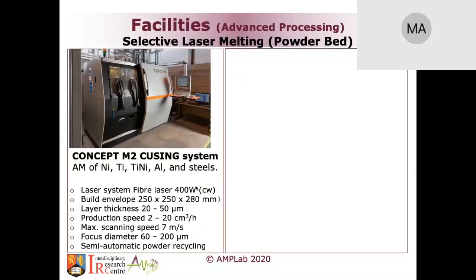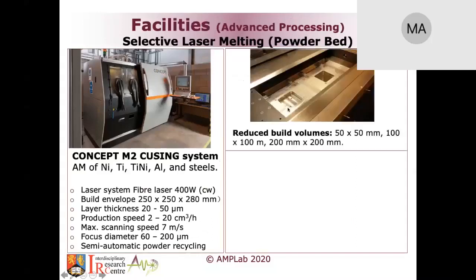One of the good things is that we've used our Concept Laser machine that we have in Birmingham. The machine has a fiber laser, of course, 400 watts, and a build envelope of 250 by 250 by 280. But we have modified the machine since we got it by adding a reduced build volume, so we can actually build with very small amounts of powder. We have a substrate that is 50 by 50 millimeter, so only 5 by 5 centimeter, then another substrate which is 10 by 10, and another which is 20 by 20. So I keep telling people, if you get me a cup full of powder, we can actually process the material and make a go at processing it.